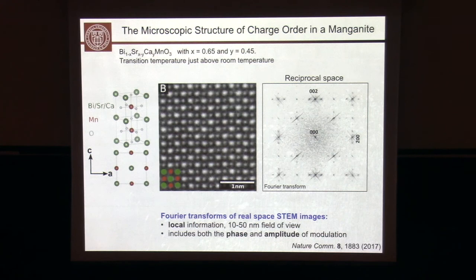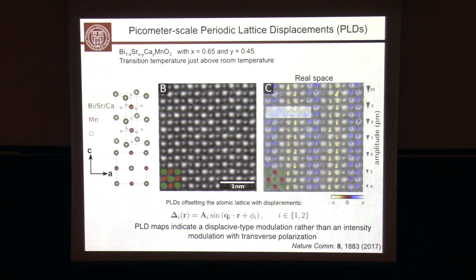All right. So now, what we have done, I'm not going to go too much into detail. With atomic peak fitting, we can actually extract how an atom is displaced with respect to the original position in the charge density wave state. And so the picture that emerges now, we have our stripes. Okay, that's the slide I had in the beginning. And you see the atoms in blue are displaced downwards by about 5, 6, 7, 8 picometers, depending.